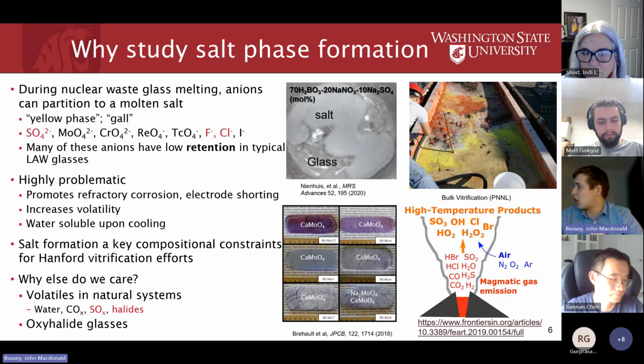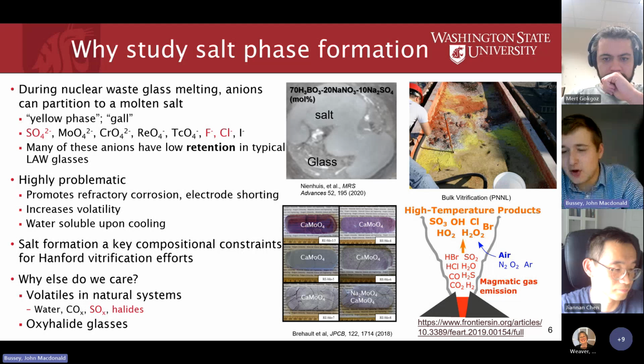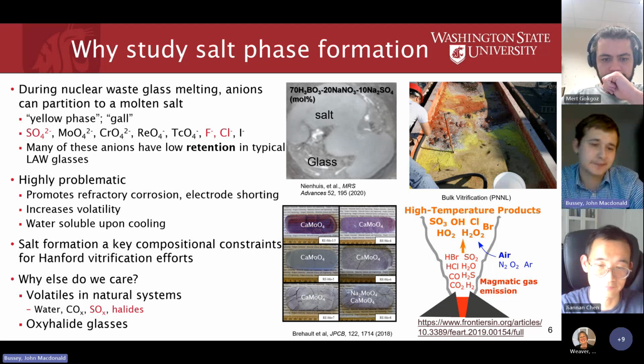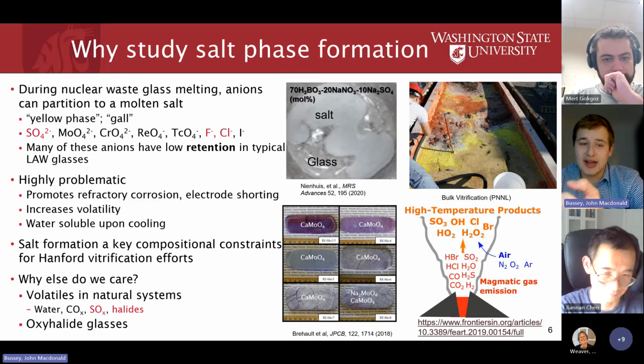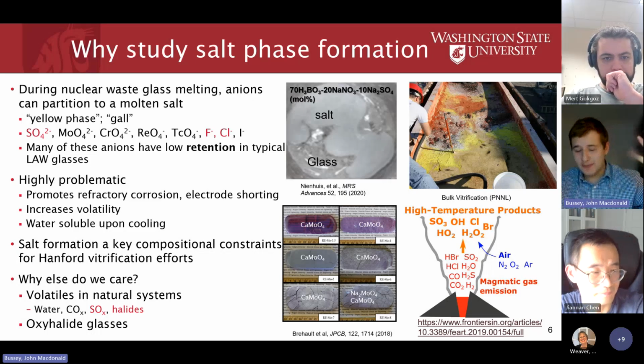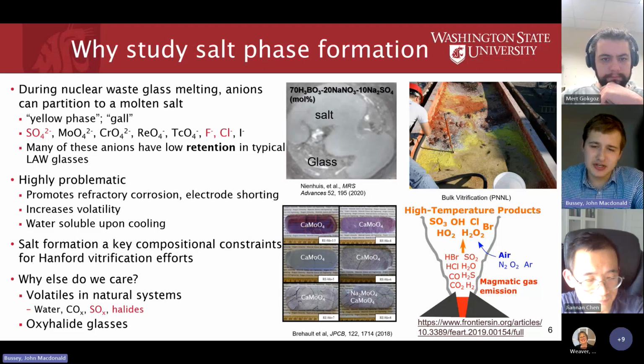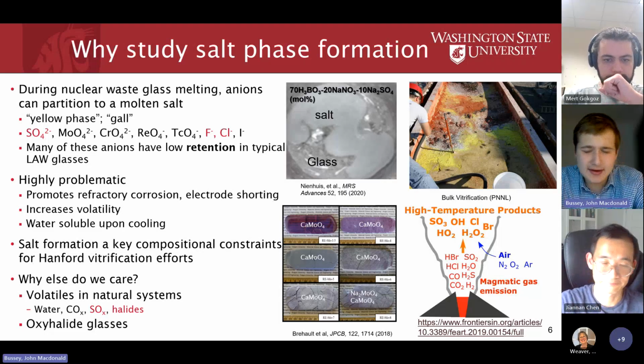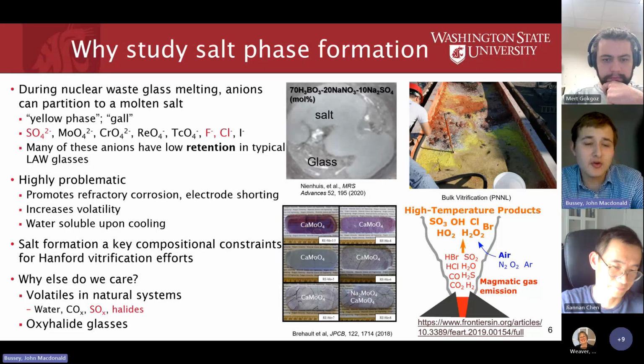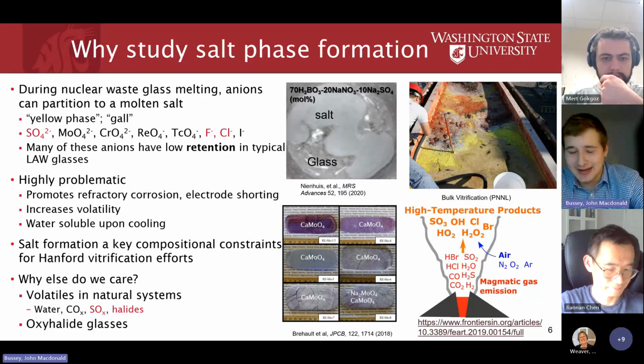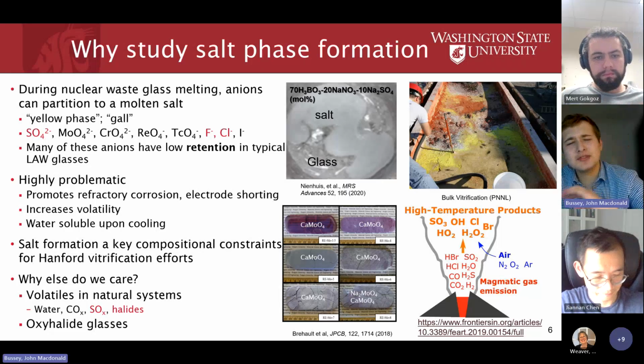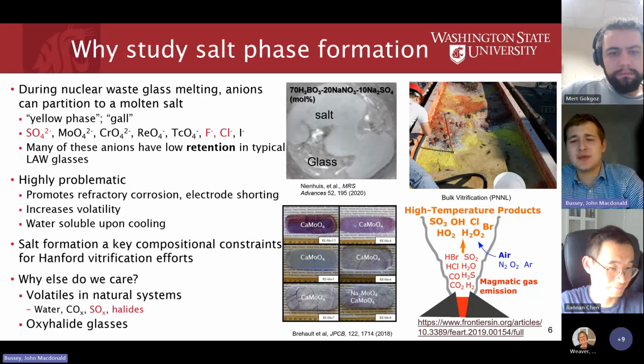The other issue is that the way these melters work is they have electrodes that go in and heat the melt through conduction. And if you have a very highly conductive salt layer on top, you'll just short out the melter. Other concerns are that these salt phases, as with the name volatiles, volatilize very quickly and go up into the off-gas system, which can be quite difficult to work with. They're also water soluble upon cooling, and they'll trap things like cesium and iodine, etc. So salt is really something we don't want, and we've seen that we've had it.